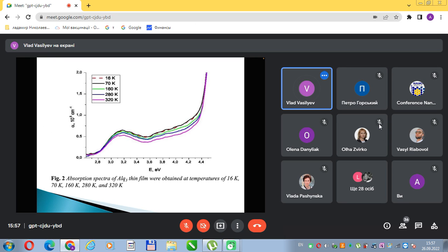At high excitation densities, the photoluminescence efficiency decreases when the temperature is reduced from 170 to 15 Kelvin, and at low laser intensity, the photoluminescence efficiency is nearly temperature independent. The observed photoluminescence quenching at high excitation densities was assigned